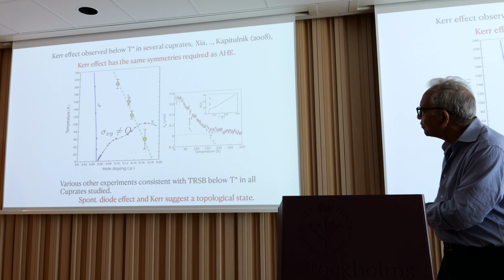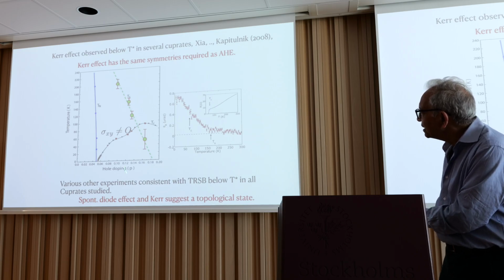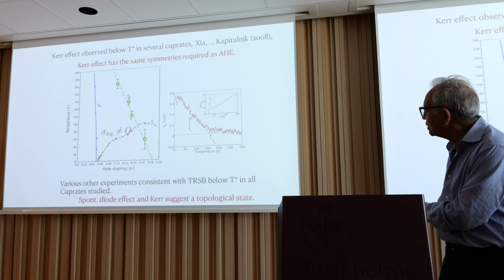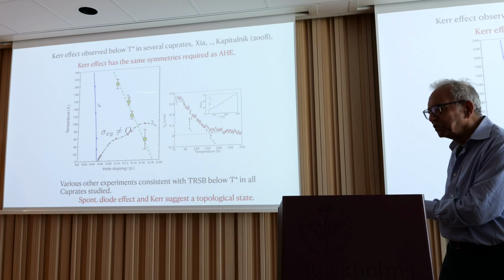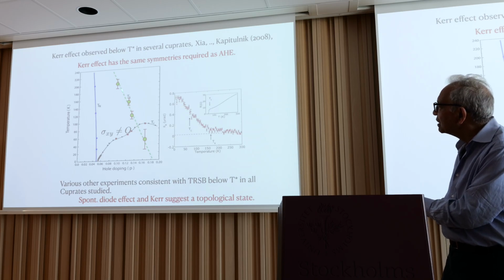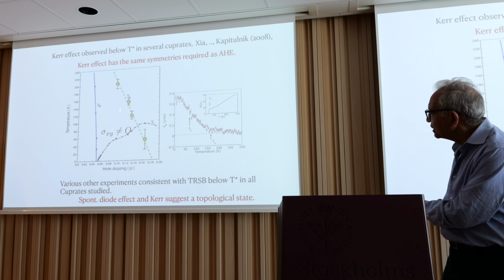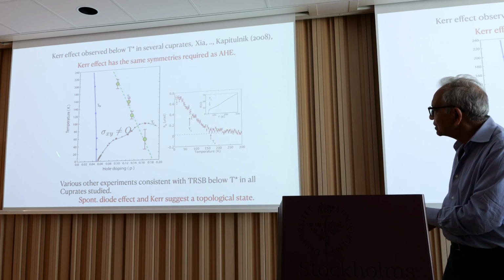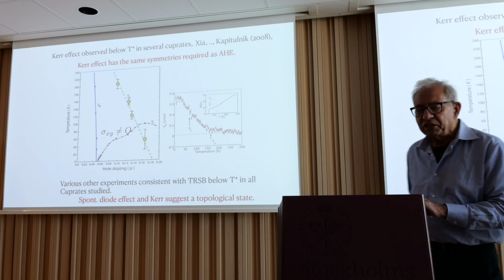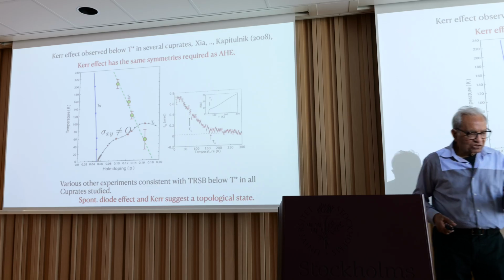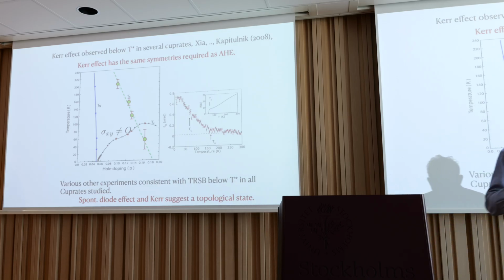And he has done this for various samples, various different dopings in a given sample. This happens to be YBCO. He also has data for BSCCO. And you see that Kerr effect is found in this range. I should say that there are a variety of experiments, neutron scattering and a wonderful experiment by Shibauchi on changing lattice symmetry on applying magnetic field below the superconducting transition temperature, below the pseudo-gap temperature, and a few other time reversal specific experiments.